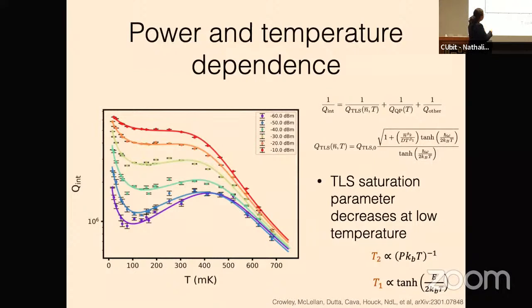So let me just quickly walk you through, I know this is a somewhat complicated plot, but basically at high temperatures, you break up Cooper pairs. So you just see quasi-particle loss and no power dependence. In these intermediate temperatures, you see a lot of two-level system loss, so the powers are very different. And then this kind of gentle slope up is this hyperbolic tangent part that just comes from the partition function. So you just thermally saturate your TLSs, and then that saturates the loss.